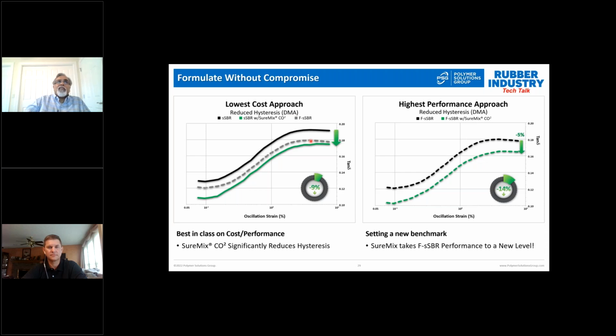And the answer is yes. If you just take the solution SBR and add SureMix to it, you'll have the lowest viscosity of all the compounds we've looked at in this section, and hysteresis that's even lower than the functional polymer. So you get the best of both worlds. You get the performance targets and the ease of mixing and processing. Furthermore, since the compound has 6 PHR of SureMix versus 100 of a functional polymer, there's a dramatic reduction in compound cost, as well as compound stability, because functional polymers can have quite an increase in viscosity on storage.